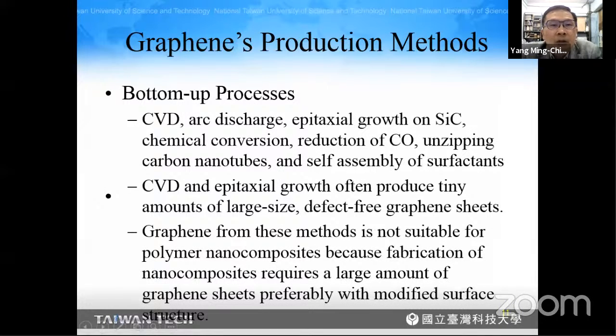Now about the first type, the bottom-up process. Here, CVD, also such as the arc discharge, epitaxial growth on silicon carbide, chemical conversion and reduction of carbon monoxide, unzipping carbon nanotubes, and self-assembly of surfactant all belong to the bottom-up process. Among these, CVD and epitaxial growth often produce a tiny amount of large size defect-free graphene sheet. And from this method, graphene is not suitable for polymer nanocomposites because fabrication of nanocomposites requires a large amount of graphene sheet, preferably with a modified surface structure.